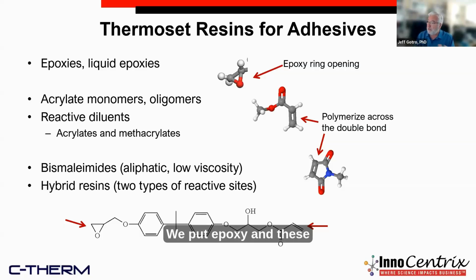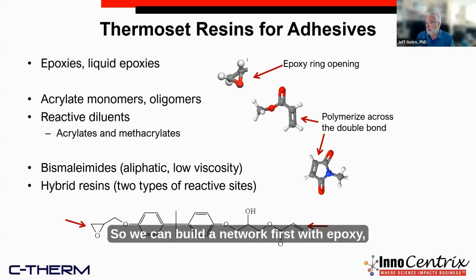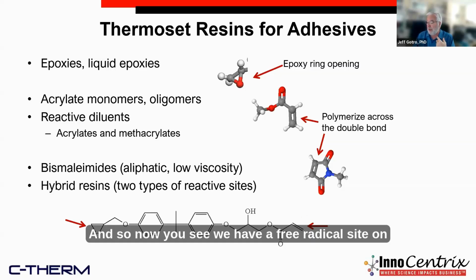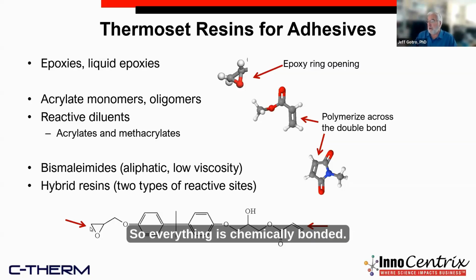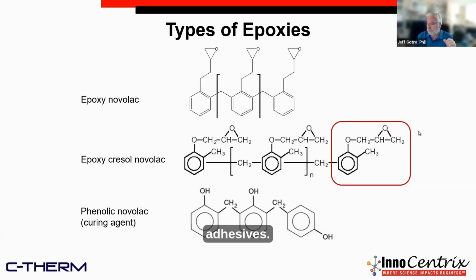And then a really interesting chemistry, in a lot of applications, we combine these. We put epoxy and these acrylates, so we can build a network first with epoxy, and then we can then initiate these free radicals that polymerize across the double bonds. So we'll have a mixture of epoxy, acrylate, or methacrylate, or bismaleimide, and we put in this hybrid. And so now you see we have a free radical site on this end and epoxy on this end, so we can tie the whole network together. So everything is chemically bonded. So there's a lot of sort of chemical molecular architecture work that we do in these types of adhesives.